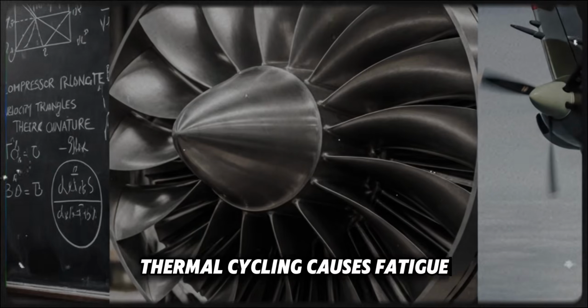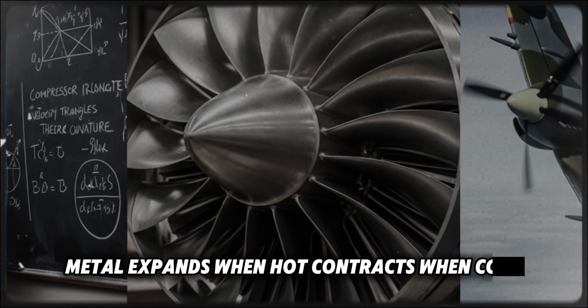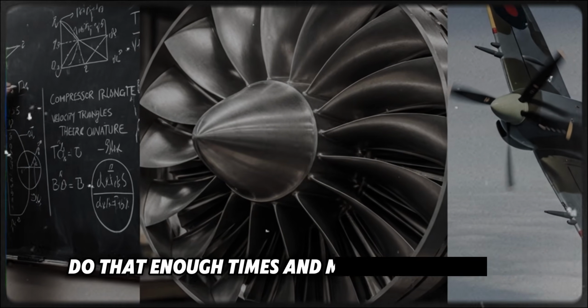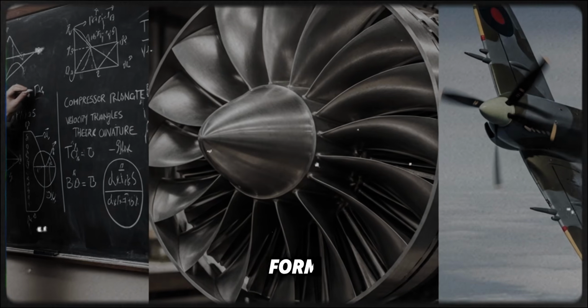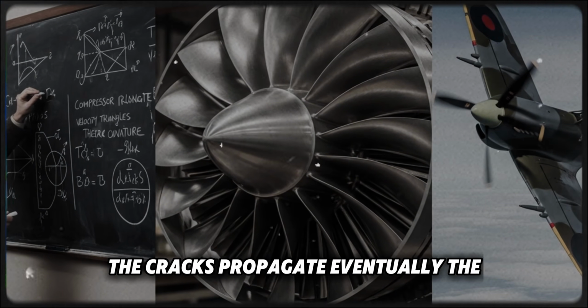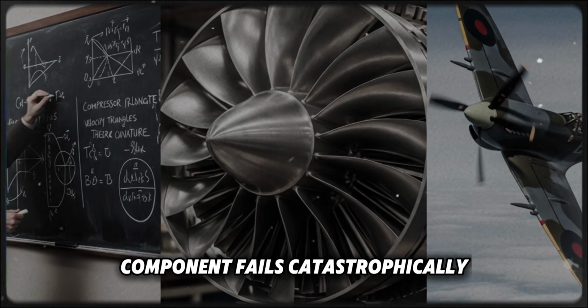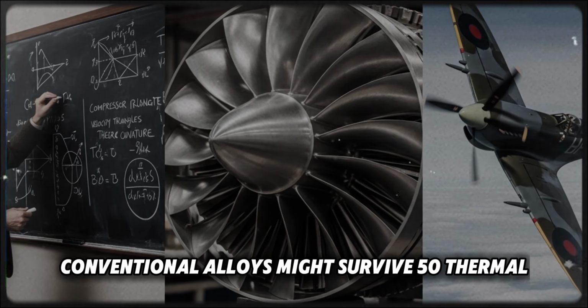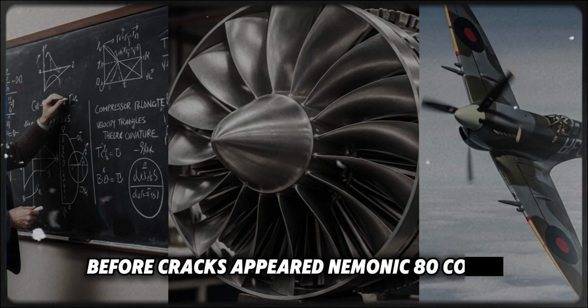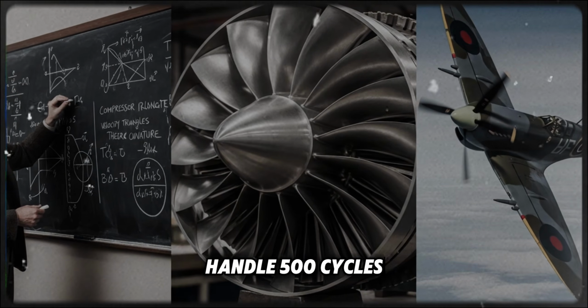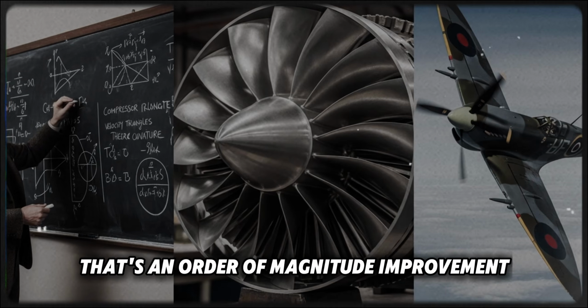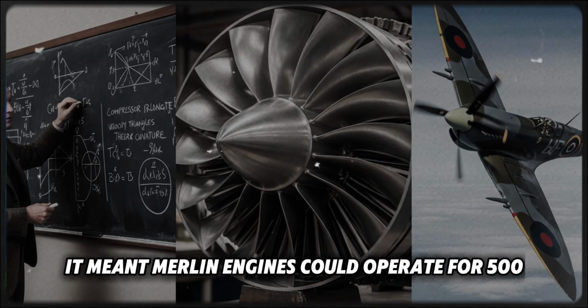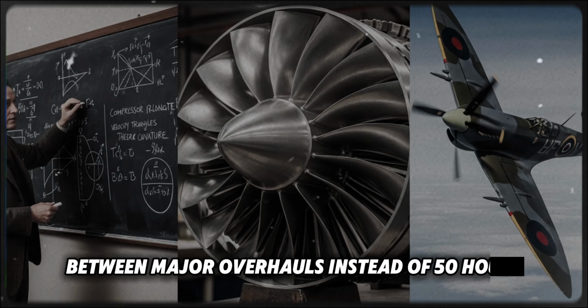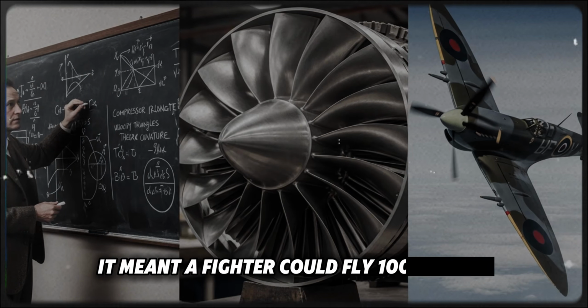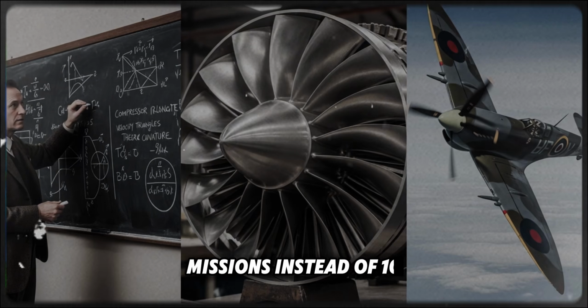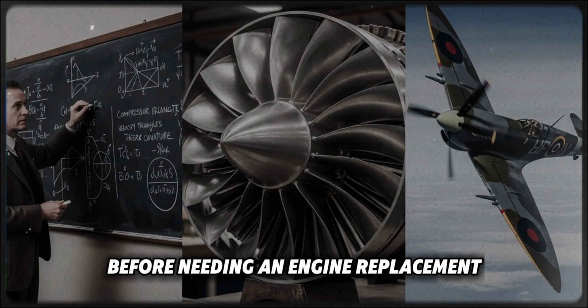Thermal cycling causes fatigue. Metal expands when hot, contracts when cool. Do that enough times, and microscopic cracks form. The cracks propagate. Eventually, the component fails catastrophically. Conventional alloys might survive 50 thermal cycles before cracks appeared. Nimonic 80 could handle 500 cycles. That's an order of magnitude improvement. It meant Merlin engines could operate for 500 hours between major overhauls instead of 50 hours. It meant a fighter could fly 100 combat missions instead of 10 before needing an engine replacement.